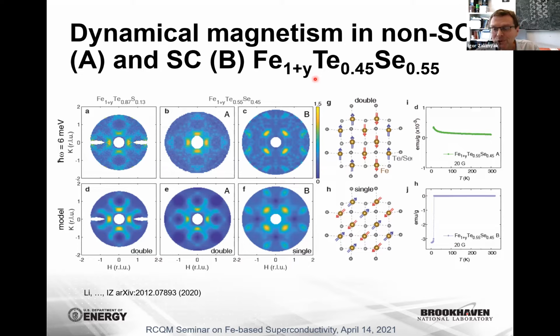If the sample becomes superconducting and undergoes a transition in a small magnetic field, which we use to guide the neutron's polarization, the neutron beam becomes depolarized. From that, we actually know that the big piece that we measured of type A is non-superconducting and causes no depolarization of the neutron beam, while this big chunk is superconducting.